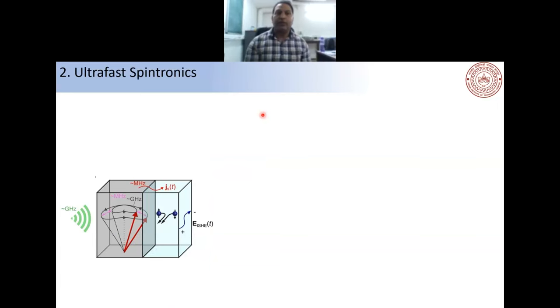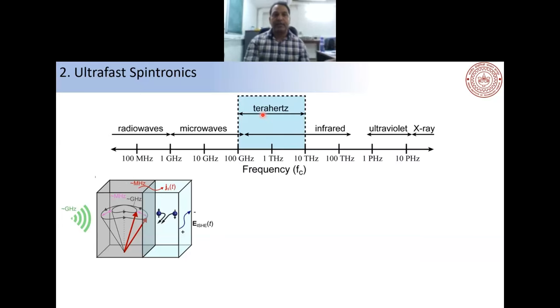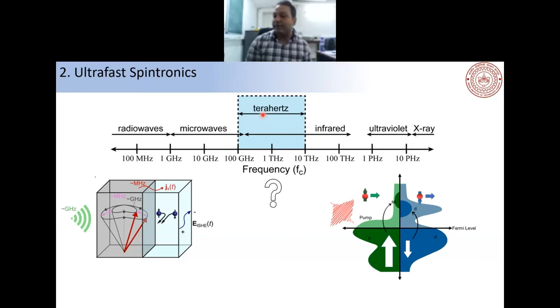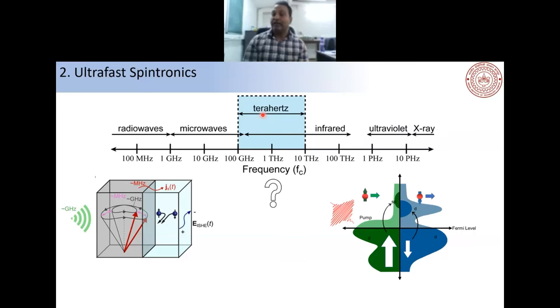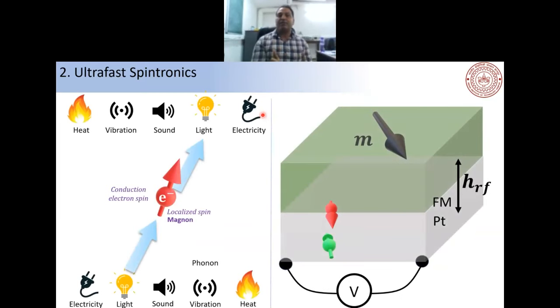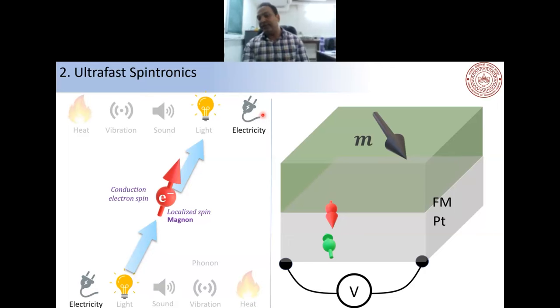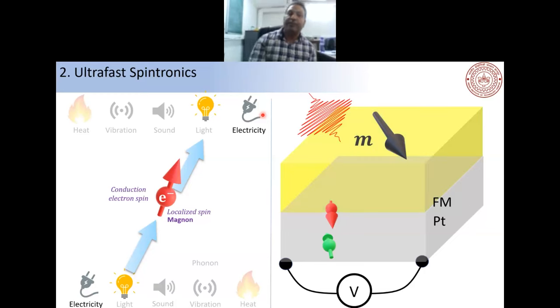We are also trying to understand this effect at ultrafast timescales. Currently we work at gigahertz frequencies using RF fields, but to reach the terahertz regime we need different mechanisms. The answer is ultrashort pulses: shining ultrashort laser pulses on ferromagnetic materials excites them out of equilibrium, resulting in ultrafast super-diffusive spin transport phenomena, which can generate ultrashort terahertz pulses. We shift from electrical measurements to optical measurements — using light to generate spin current and spin current to generate light.